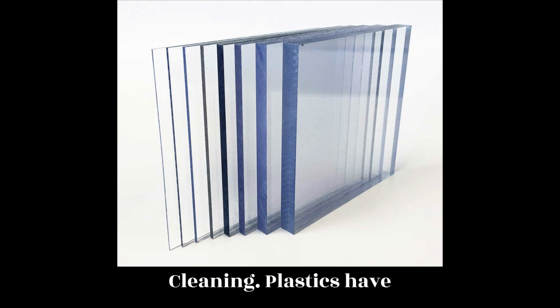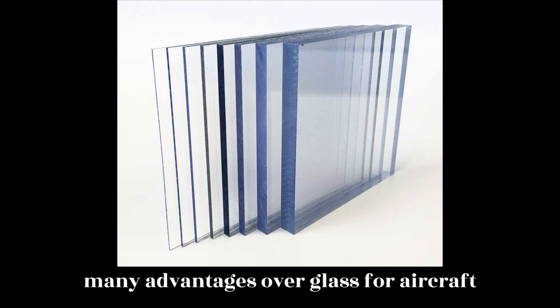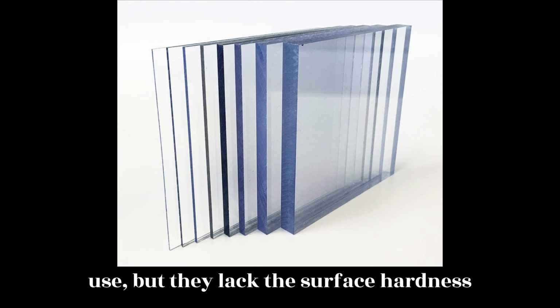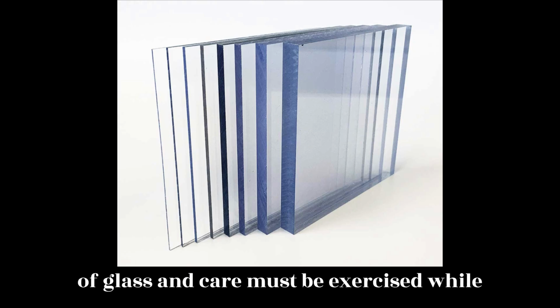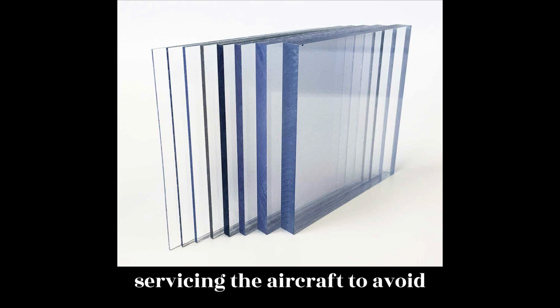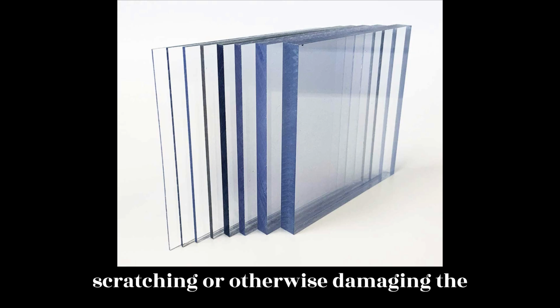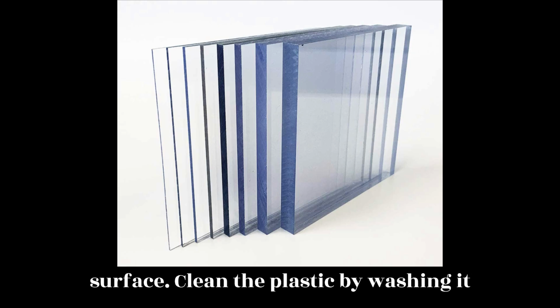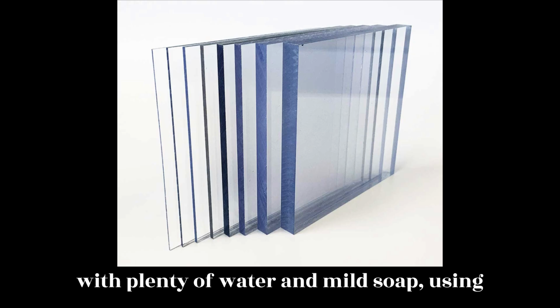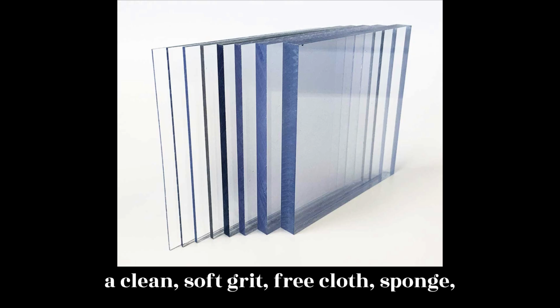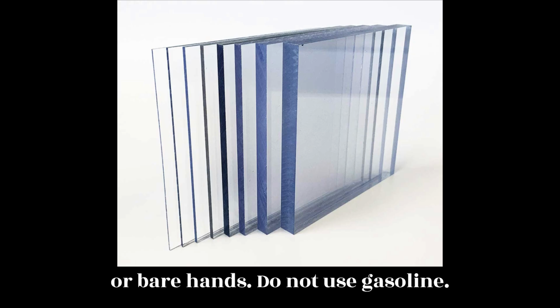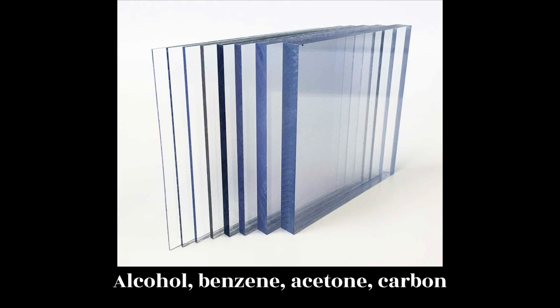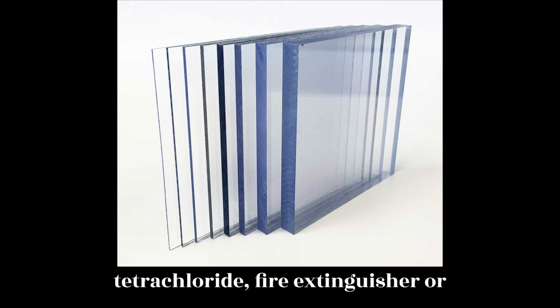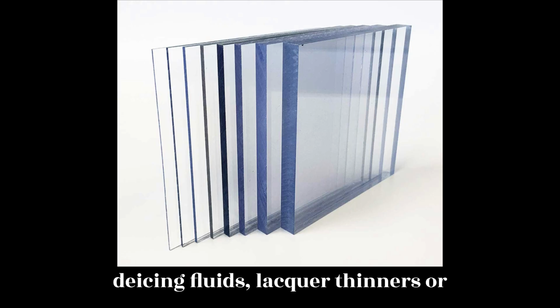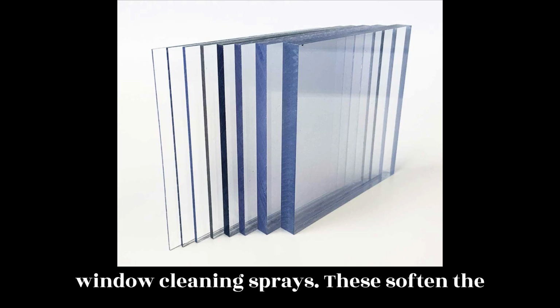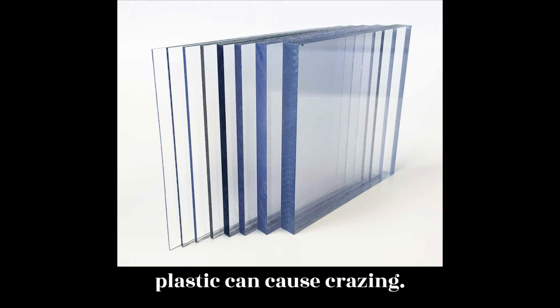Cleaning. Plastics have many advantages over glass for aircraft use, but they lack the surface hardness of glass, and care must be exercised while servicing the aircraft to avoid scratching or otherwise damaging the surface. Clean the plastic by washing it with plenty of water and mild soap, using a clean, soft, grit-free cloth, sponge, or bare hands. Do not use gasoline, alcohol, benzene, acetone, carbon tetrachloride, fire extinguisher or de-icing fluids, lacquer thinners, or window cleaning sprays. These soften the plastic and cause crazing.